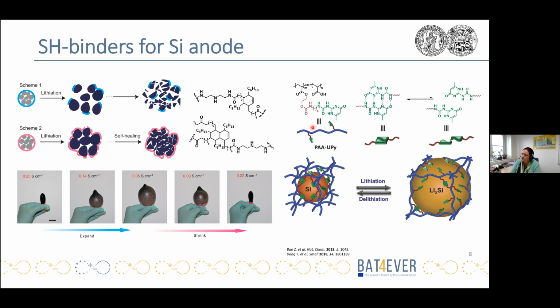The incorporation of the UPy groups results in the formation of this kind of supramolecular polymer network around the particles, which offers a strong adhesion strength with a silicon nanoparticle, and was able to withstand large volume expansion and the release of the internal stress of the particles during the lithiation and delithiation processes.